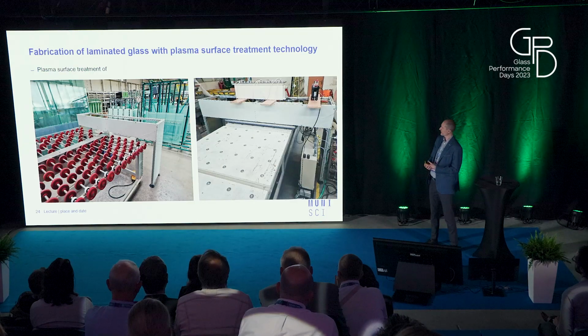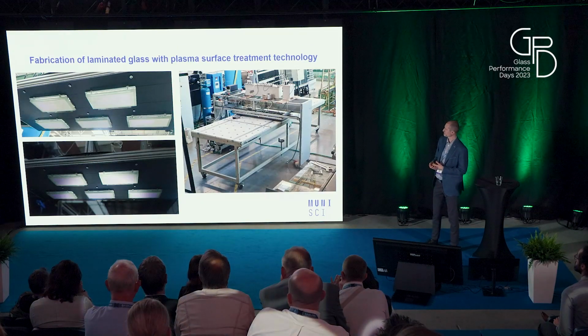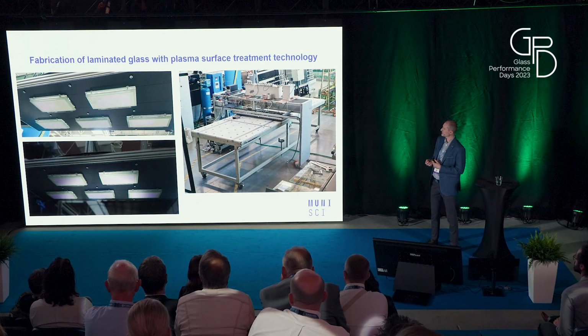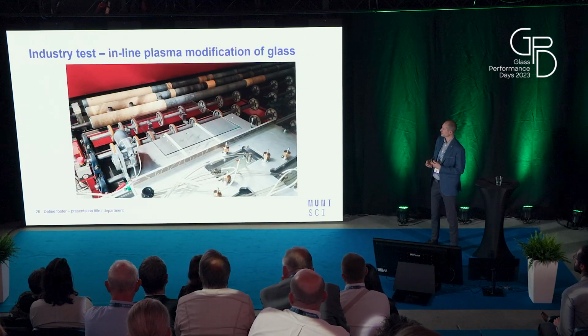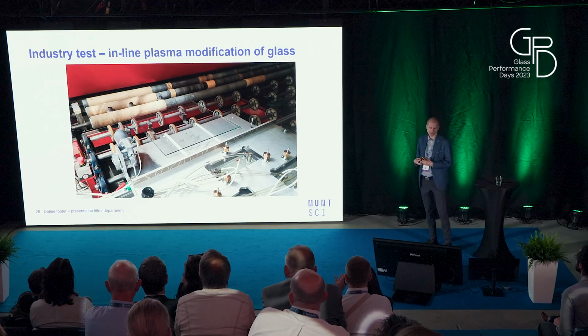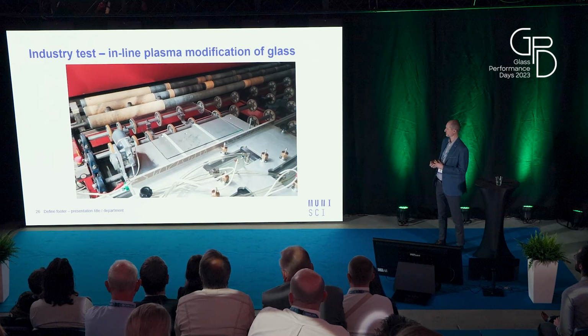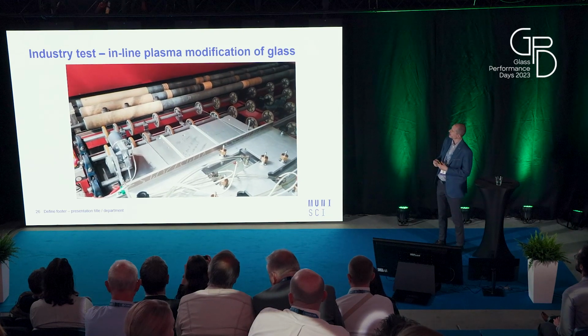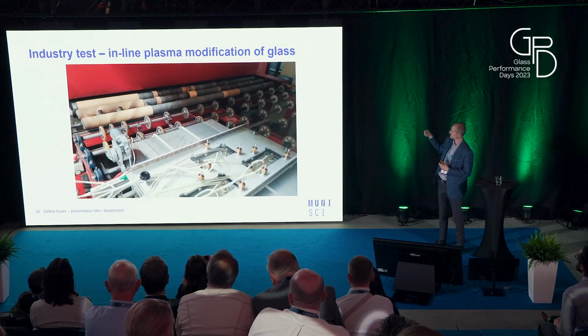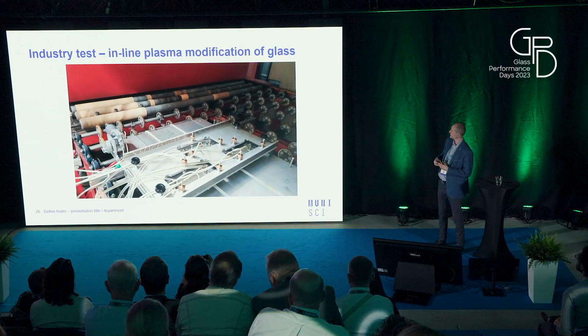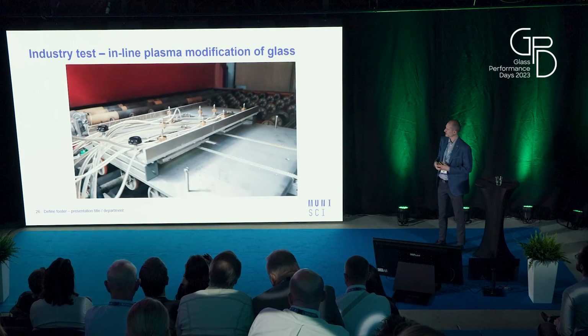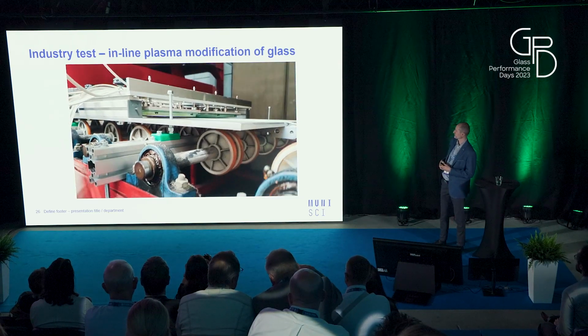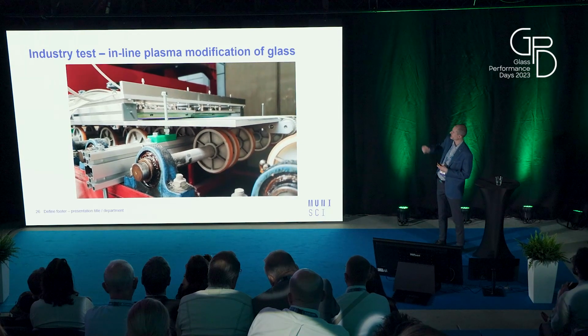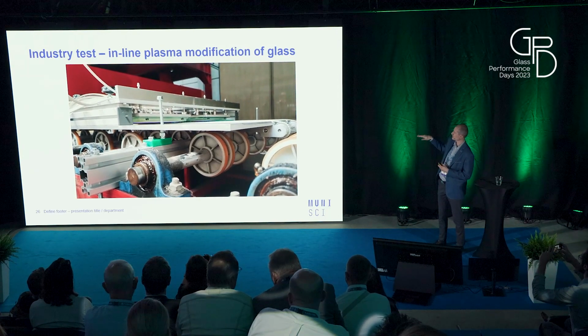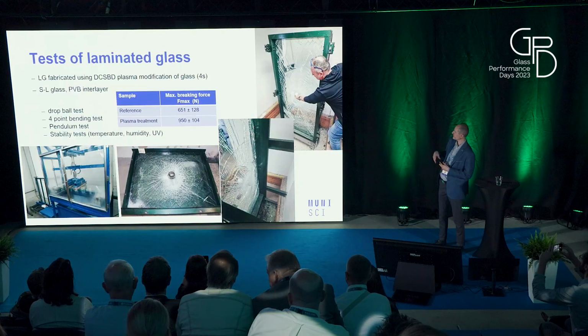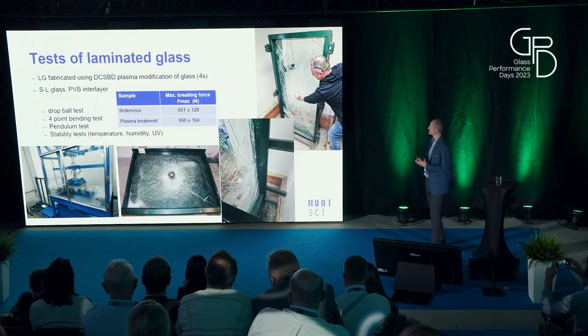So, the application. We plasma-treated glass, and we created laminated glass. We did the experiment also in a real production line for laminated glass. This is one section. The machine direction is from the left to the right. The glass is coming from the washing machine, and then on the right-hand side, there is the real lamination process. You can see how the glass is treated by plasma when it passes through the plasma region. We took this glass and then we analyzed it.